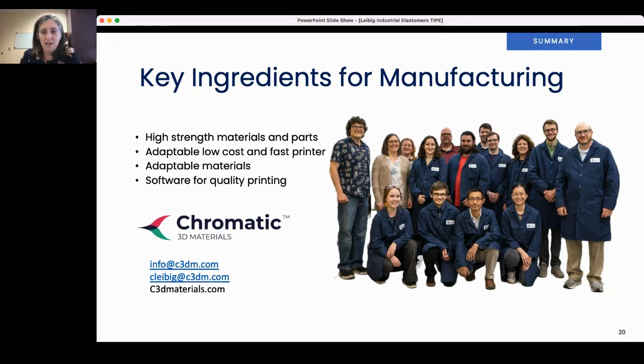I see one question about range of dimensions, how big and how small. In terms of size of part, we prefer to have parts that are about, let's say, 2 inches in diameter and bigger. We've been able to print parts as small as a centimeter in diameter and about an inch tall. But the technology is really well suited for large parts. The largest part we've ever printed is about 4 feet tall, and we've also printed parts that are even 5 feet long. So we're able to go quite large and bring that value proposition of a good solid part to the table there.